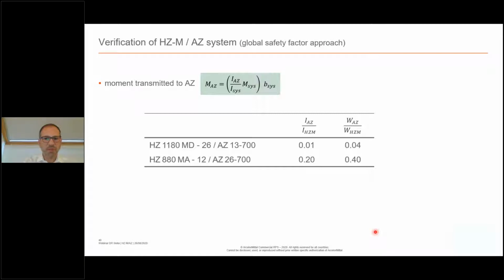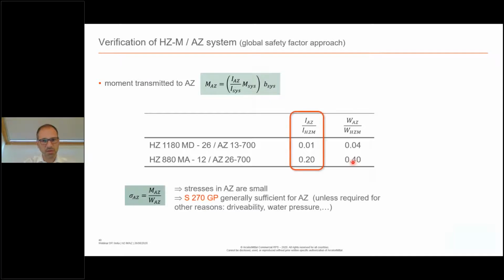And in this table, you'll see that, for instance, for a very big king pile and the lightest infill sheet, which is the AZ13700 or the 770, you see that the inertia of the infill sheet is about 1%. So almost all the bending moment goes into the king pile. Whereas if you take a smaller king pile like the 880 MA and a larger infill sheet, in that case, you might have 20% of the inertia ratio, so that a little bit more of the bending moment will be taken by the infill sheet. In this case, it would be around 40%. But this is also something that you can calculate with the software.